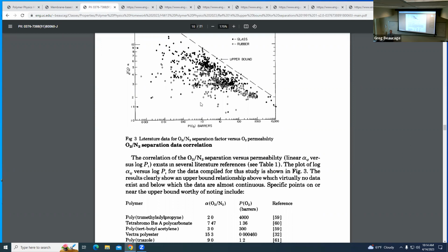If it's compatible, then it plasticizes the membrane. If it plasticizes the membrane, the free volume that you're trying to punch through can either compress or release, so it can change the transport. The fact that you're driving the thing through means you're kind of putting a solvent into it, and that changes the transport properties. That can drop your selectivity, because if you have looser pores that you're pushing through, then it's not as selective. The rigidity of the pores is what's selecting. They aren't pores like molecular holes, but free volume in the material, right? So anyway, that's kind of the idea of this, more or less.